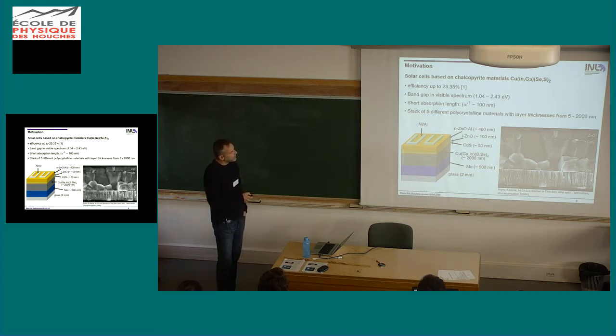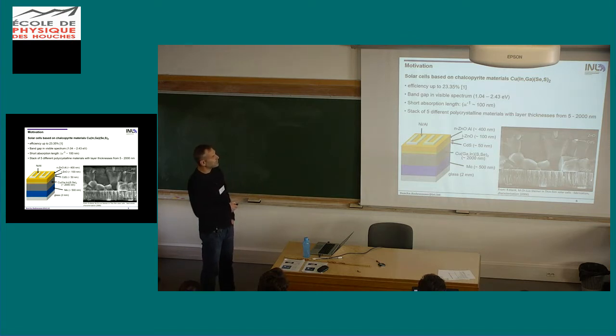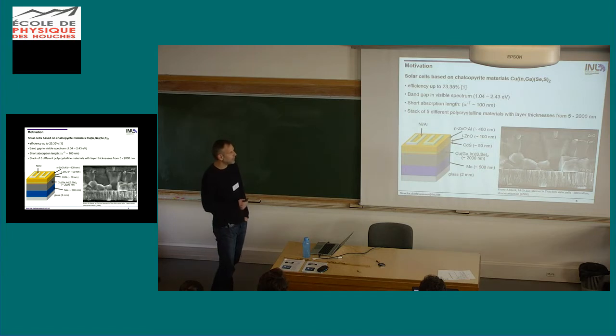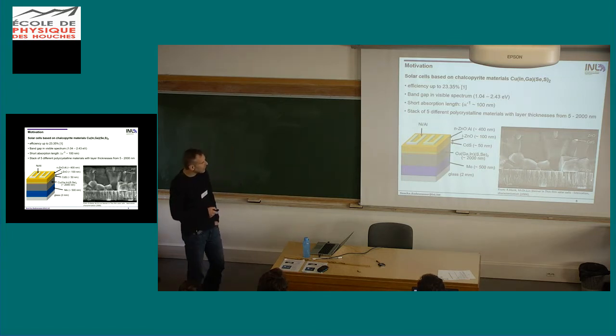By varying indium, gallium, or sulfur and selenium composition, we can vary the band gap between 1 and 2.4, which includes the visible spectrum, so it's very suitable material for solar cell applications. Also because it has a very short absorption length, we need only a thin layer to absorb all the light.